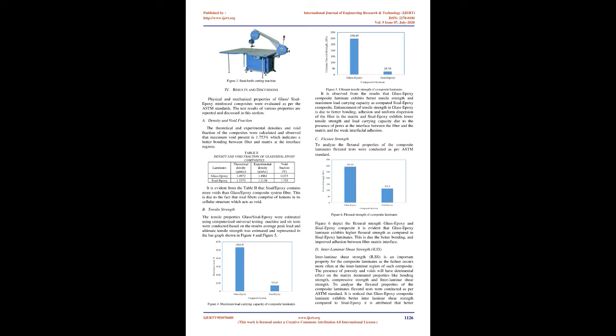Initially, the number of layers of the sisal/glass fibers is marked and cut as per the required dimensions from the sisal/glass mat strands with the help of a marker and scissors. The number of layers is chosen based on the thickness of the laminate. In the next step, the calculated amount of matrix resin along with hardener is mixed. The first layer of the sisal/glass fiber is placed on a flat surface which is cleaned with the help of acetone. The first layer is coated with a layer of resin either through a spray gun or through a brush. A similar procedure is followed until the required thickness of the laminate is obtained.